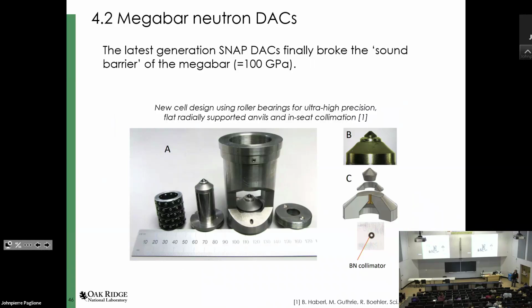Additionally, Riley designed a whole new set of diamond anvil cells, which are based on these roller bearings here. When you have a diamond anvil cell, anytime you apply load and your anvils misalign while you apply the load, the anvils break. When you are applying 7 tons or 10 tons, this gets even more severe. So our biggest problem was having cells machined to the perfection we needed so that we wouldn't misalign the anvils as we compress. This is what was addressed with these roller bearings. Now the piston, where we push on, is guided into the cell with these roller bearings, and we don't have any misalignment any longer. This has really been the breakthrough that allowed us to get to 100 GPa.